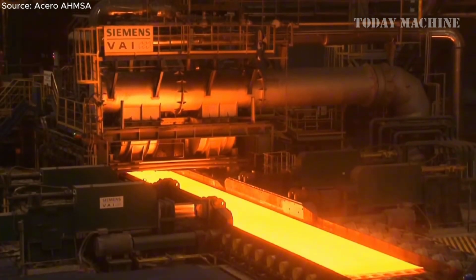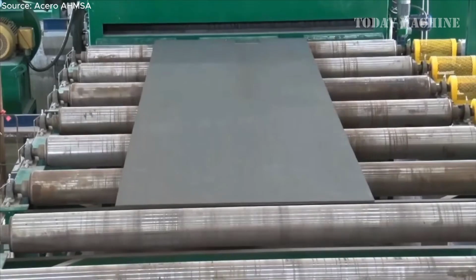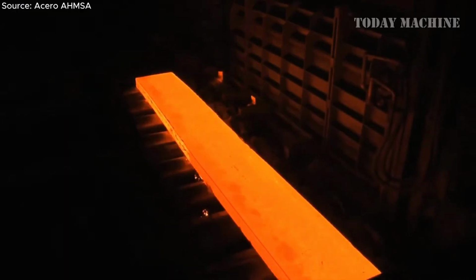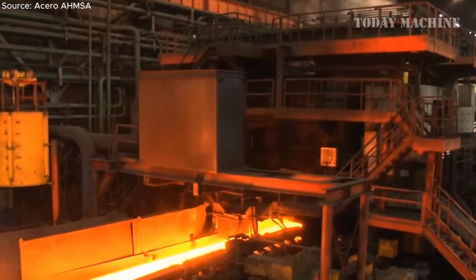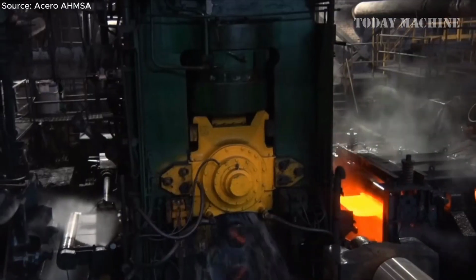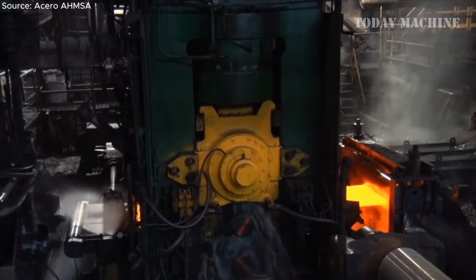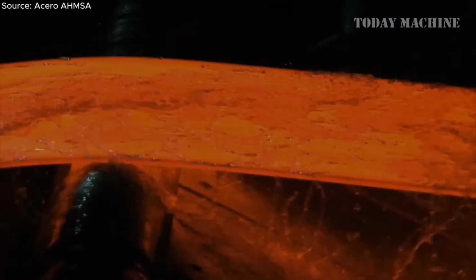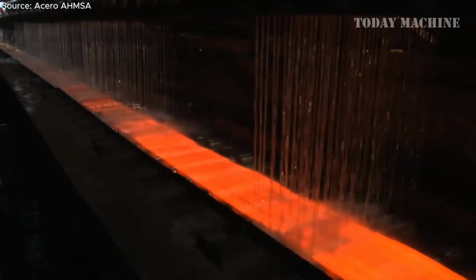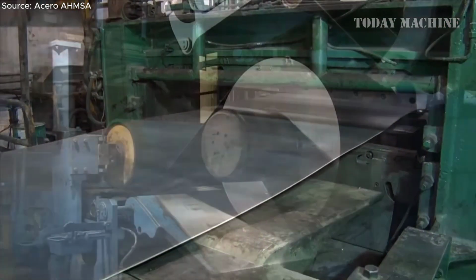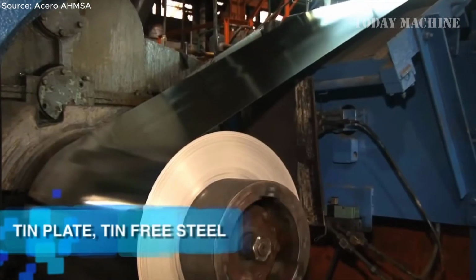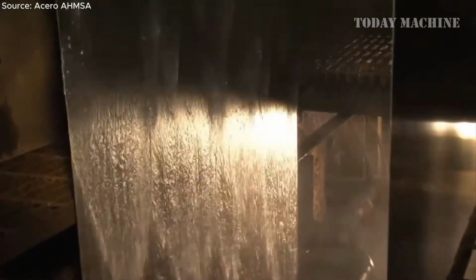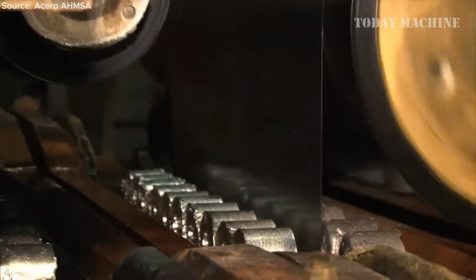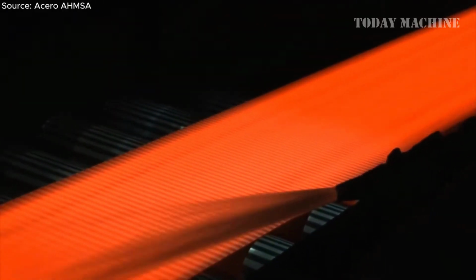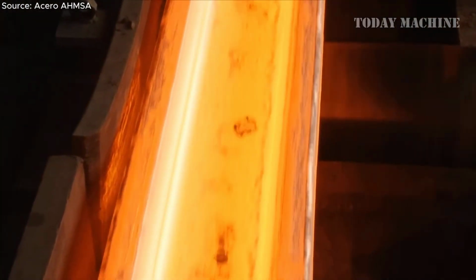This pig iron is then refined using either a basic oxygen furnace or an electric arc furnace, where high-pressure oxygen and electrical energy purify and convert it into liquid steel. The molten steel is cast into slabs through continuous casting, then processed in hot and cold rolling mills to achieve precise thickness and mechanical properties. Additional treatments, including annealing, skin pass rolling, and tension leveling, enhance uniformity and surface quality. To improve durability, steel may undergo tin plating or tin-free coating.